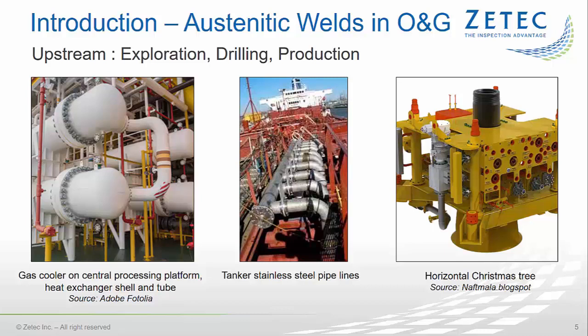In topside construction, the incoming mixture of oil, gas, and sand in the main process piping requires resistance to seawater, erosion, hydrogen sulfides, and carbon dioxide. The addition of high temperatures, high pressure, and highly corrosive fluids requires the use of high-grade austenitic materials. In subsea wellhead equipment and Christmas trees, duplex materials are used because they are less sensitive to stress corrosion cracking.